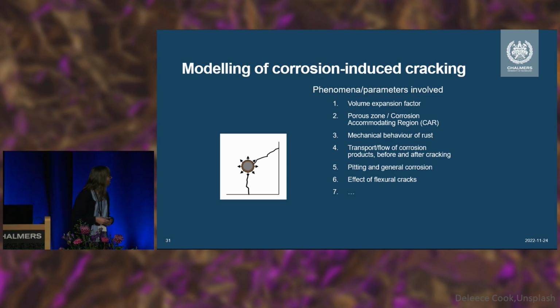Like the ones I'm lining up here, you need to know about the rust versus the steel, how large the volume expansion is. You need to know that there's a bit of a porous zone surrounding each bar. And if the rust just grows in this porous zone, it causes swelling, but it doesn't cause any stresses yet. So we need to know how big that one is. Next in line is the mechanical properties of the rust itself. It wants to expand a lot, but the concrete will push it back. So depending on how stiff the corrosion products are, you will get small or large stresses.